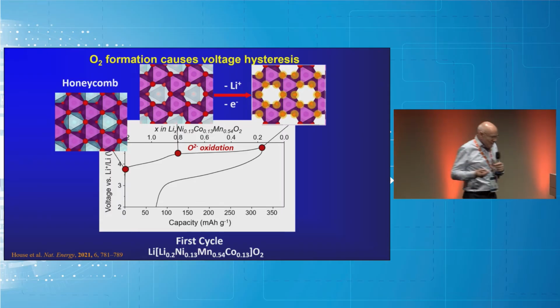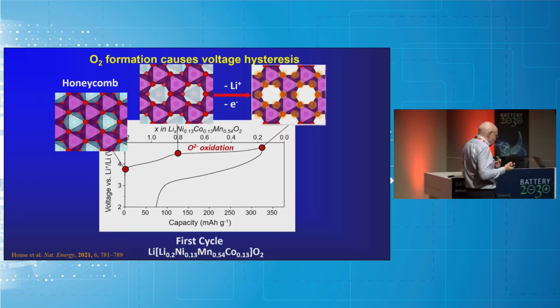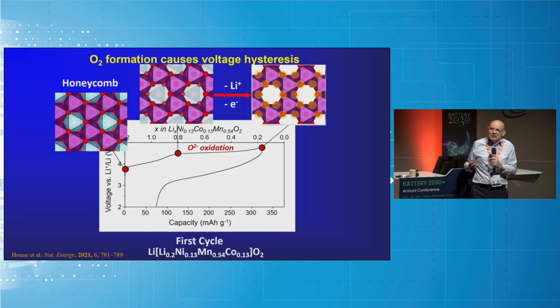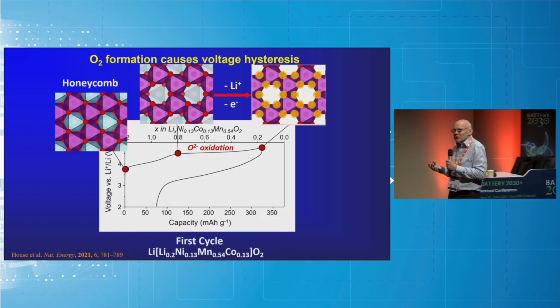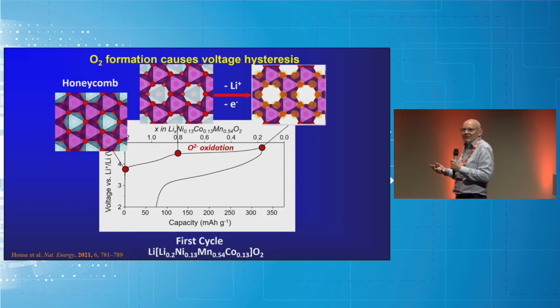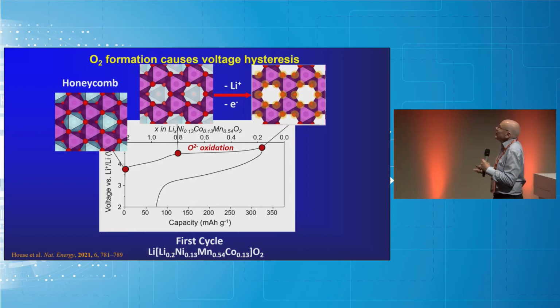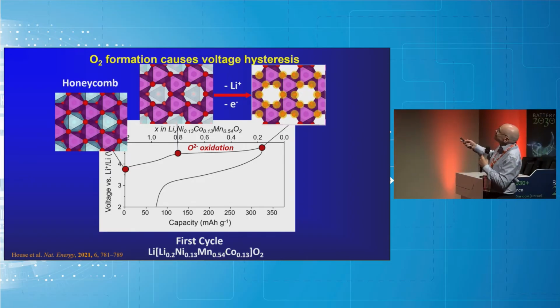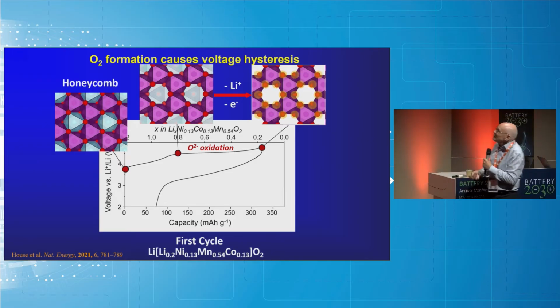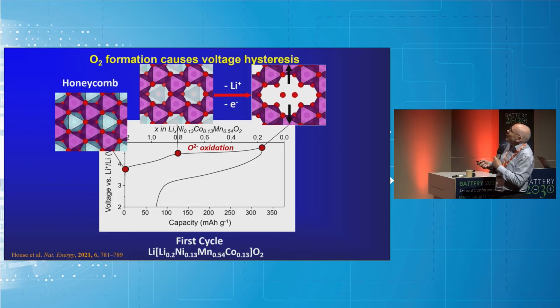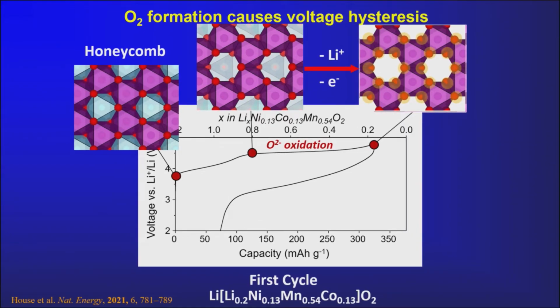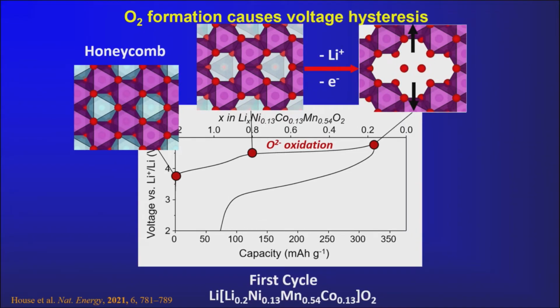What you're really doing, being brutal, is decomposing the metal oxide back to its constituents, oxygen and the metal, which is part of why it's O2 that you get when you do this kind of thing. You're taking electrons out of the valence states. So you're weakening the metal-oxygen bond. That makes the movement of manganese, or any other transition metal ion, easier. So all that has to happen is that. I'll just do that again. If you keep an eye on these two transition metal ions, all they have to do, those movements, to create a nanovoid, a cluster of vacancies.